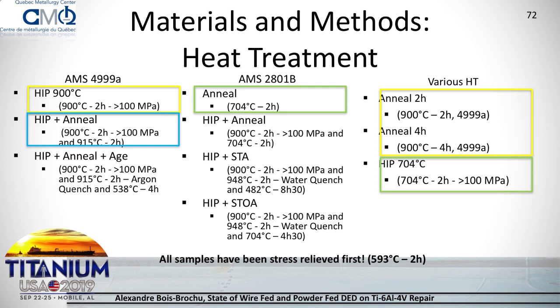Meanwhile, as you'll see, the requirements cannot be reached with those conditions in certain compositions like grade 23. So we applied various heat treatments that are allowed between the AMS 4999A and the AMS 2801B, which is a standard for heat treatment, and different heat treatments based on variations of that. As you can see, we've also used only hipping and compared it with the condition without hipping, so same heat treatment condition but removing the pressure.